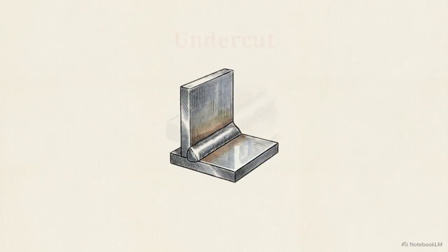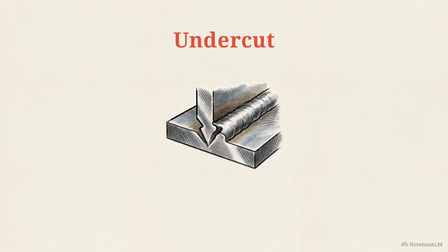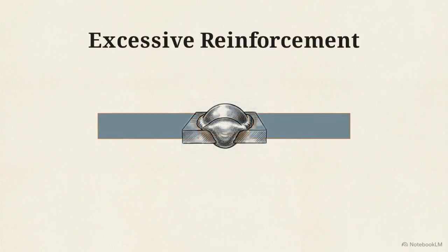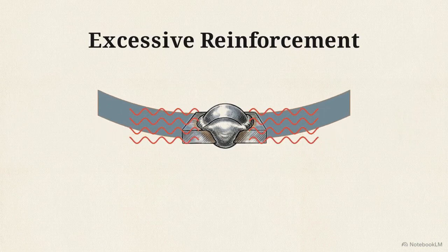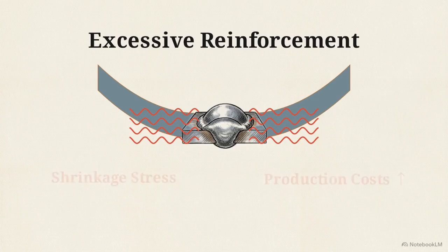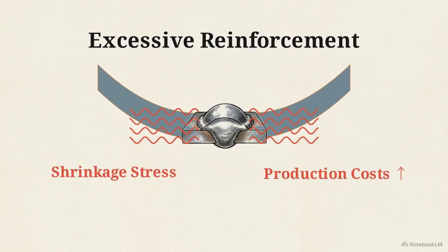They measure for undercut, a specific defect where a groove is melted into the base metal at the toe of the weld. That narrow groove physically weakens the surrounding structure by concentrating all external load forces into a single fragile point. They also check for excessive reinforcement. A weld cap that sits too tall is an automatic visual fail. The extra mass adds unnecessary shrinkage stress to the plates, warps the metal, and inflates production costs.